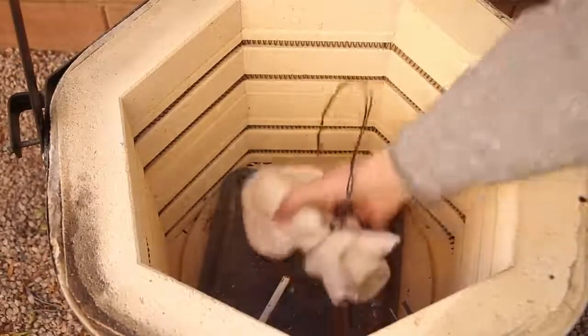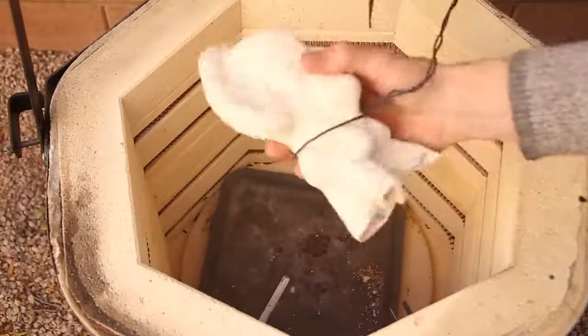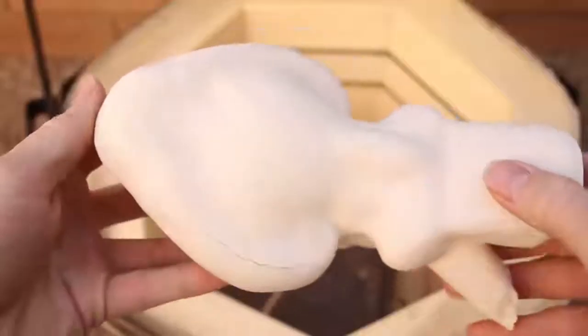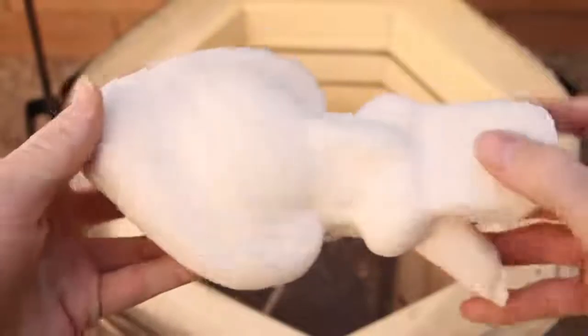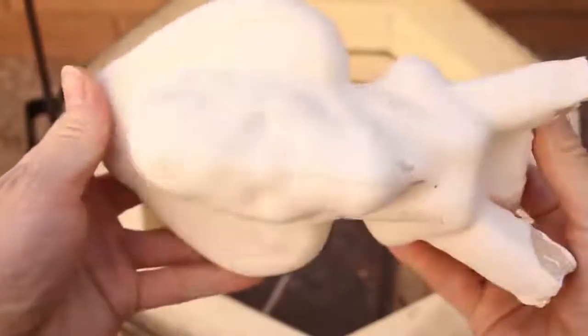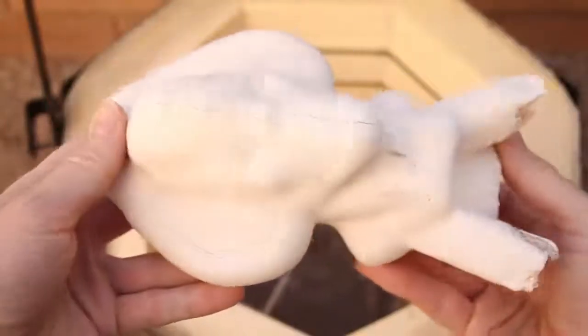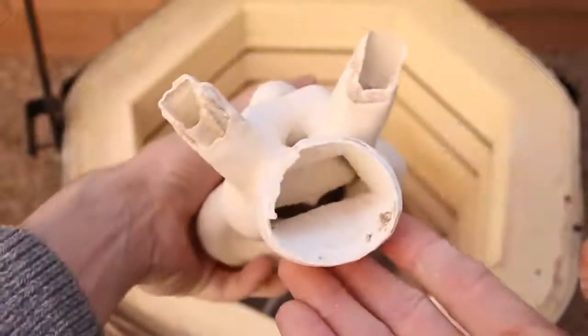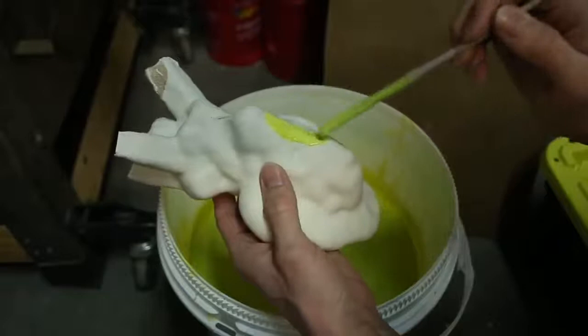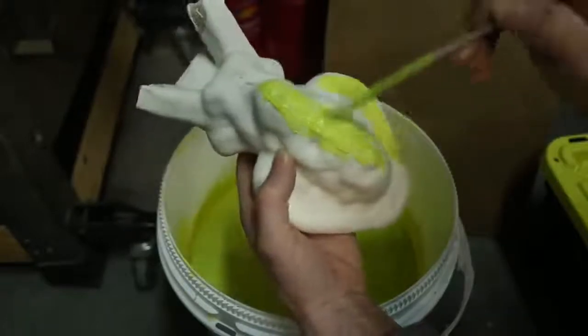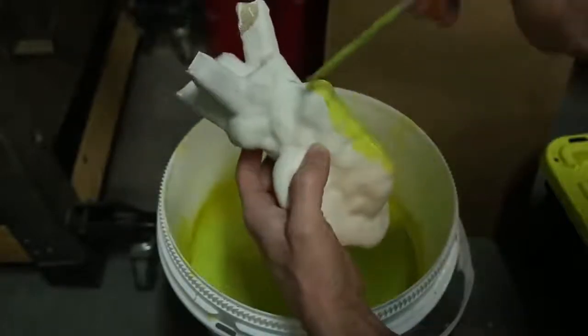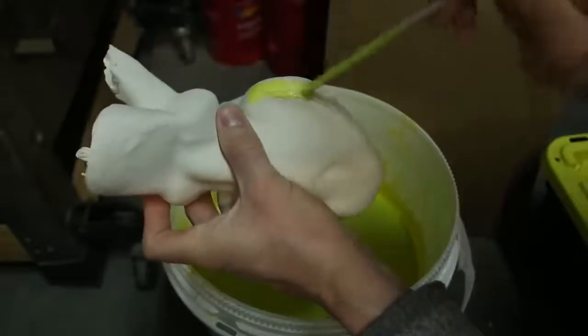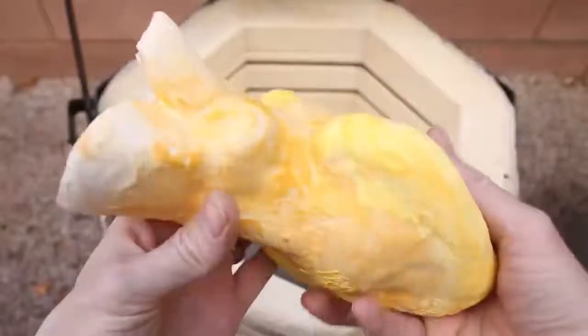The next day, I opened the kiln to discover that despite my efforts, the shell had cracked quite badly. I also noticed a large amount of ash left behind from the plastic. To try and fix the cracks, I simply painted on some more ceramic material and baked the shell again.